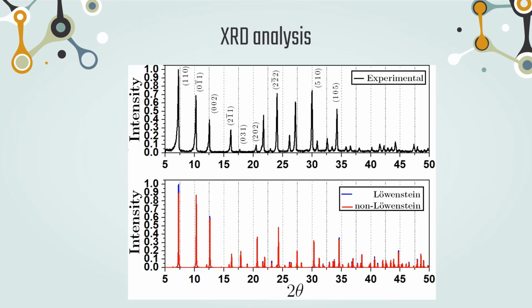This figure compares the experimentally obtained diffraction pattern for the sodic A zeolite versus the simulated diffraction pattern for the Lowenstein and non-Lowenstein configurations. The figure shows that much of the pattern of the experimental sample is reproduced by the optimized theoretical models. On the other hand, the contrast of the theoretical diffraction patterns exhibits certain differences that could be used to further interpret the experimental results.